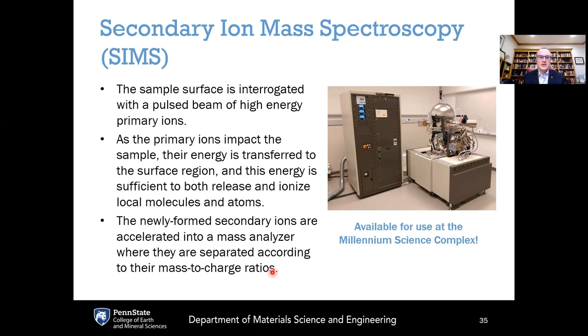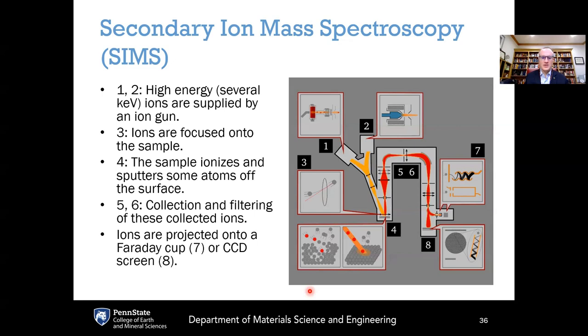The first technique is called secondary ion mass spectroscopy, or SIMS. In this case, a sample is placed in the SIMS instrument, and a beam of primary ions impacts the sample. They transfer their energy to the surface region of the sample, and that is enough to both release and ionize the local molecules or atoms from the sample itself. So the sample is being bombarded with an ion beam. It's releasing its own ions from the surface. Those are called secondary ions. Those secondary ions are accelerated into a mass analyzer, where they are separated by their mass to charge ratios, which then allows you to get the concentration profile of each of those.